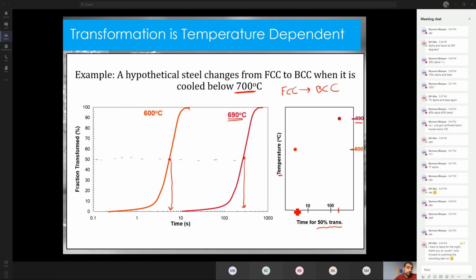And I can do this for, again, one more temperature. Let's go to an even lower temperature, 500 degrees, and we get another curve. And you might be surprised now, wait a minute, I cooled it even more, right? That's like taking liquid water down to minus 200 degrees. And I'm saying in this example here, where FCC goes to BCC, rather than the transformation happening more quickly, it actually slows down. It slowed down compared to the 600. 600 was finished within 10 seconds. 500 is taking almost 100 seconds. So why is that solid-solid transformation different from the freezing of water?